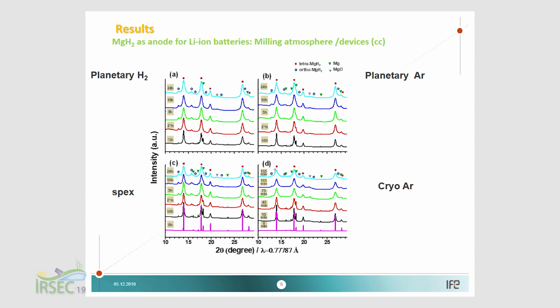We started with some work to see what morphology change occurs when we synthesize different materials from magnesium hydride, and how the morphology and properties can change. So we synthesized different materials, with different ball-milling conditions, and I will not go into the details. From X-ray diffraction it's not easy to see the difference between the materials, but we could see that the materials from reactive ball milling under hydrogen conditions are much purer.